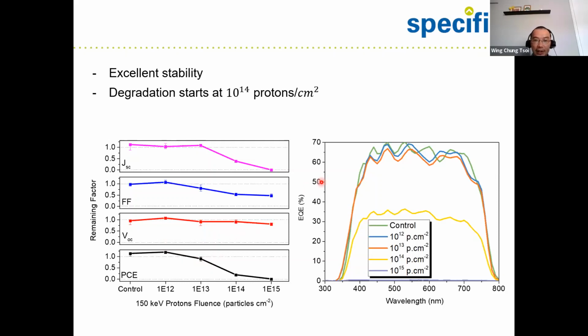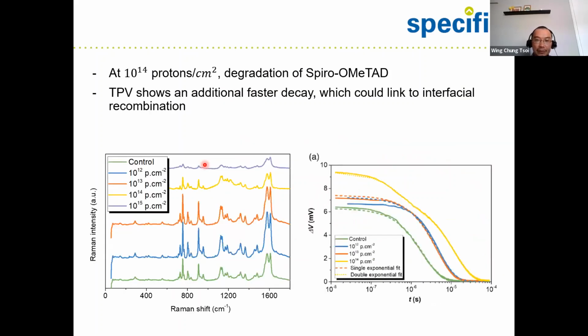And then we tried to understand what caused the degradation at 10 to the power 14 protons per centimeter square. So we did some characterization. This spectrum shows that for the external quantum efficiency, the degradation follows very similarly the drop of the short circuit current density. We think the degradation is likely due to the hole transporting layer rather than the perovskite itself, because when we did XRD on the perovskite, there was basically no observable change in the crystal structure. So we started to look at the organic hole transporting layer.